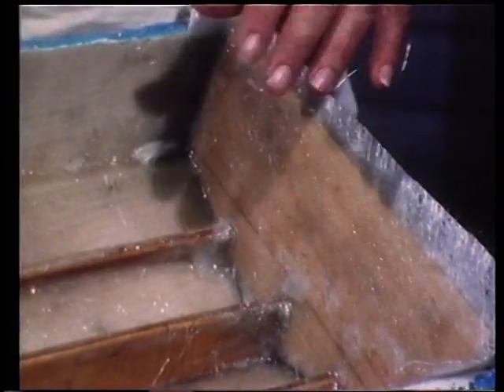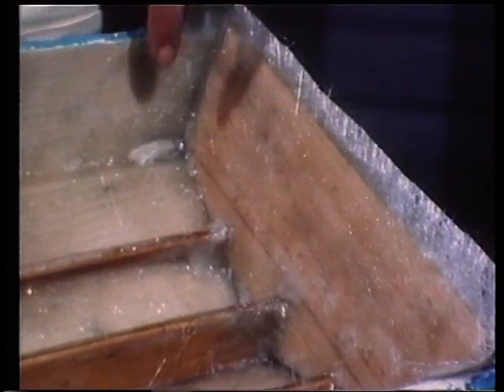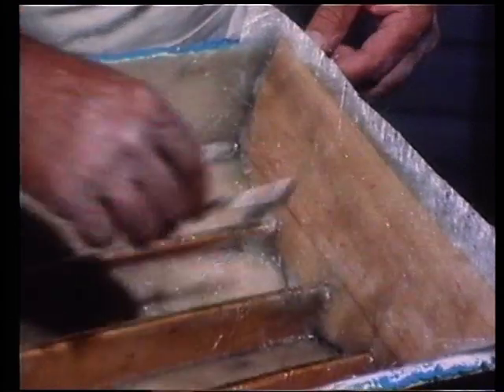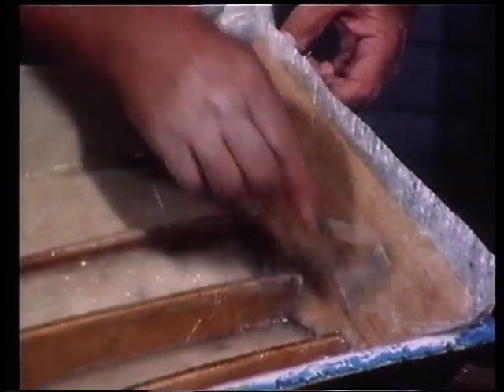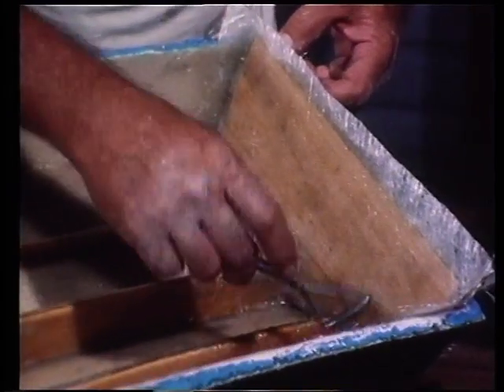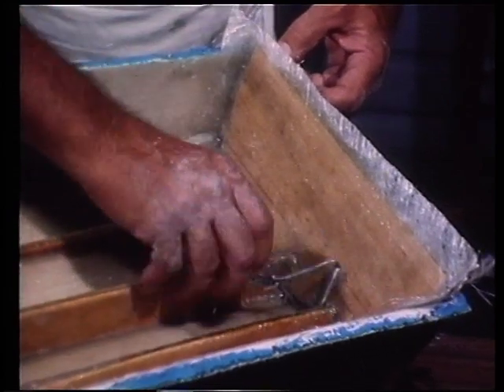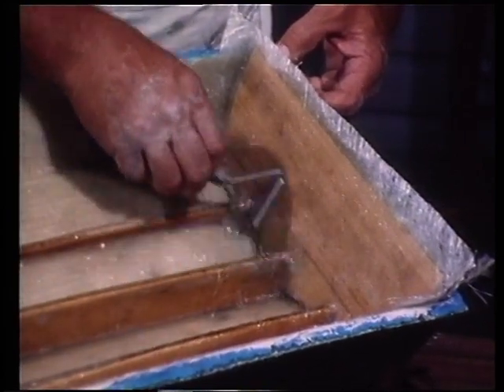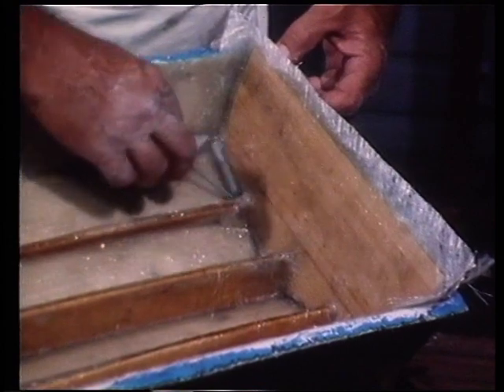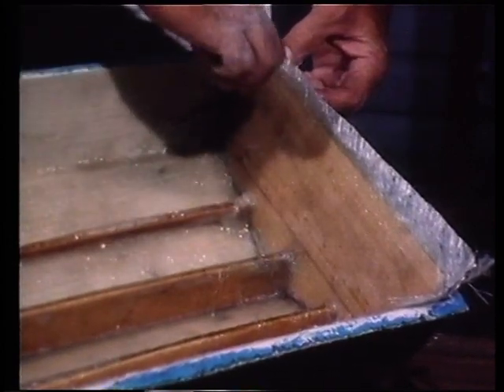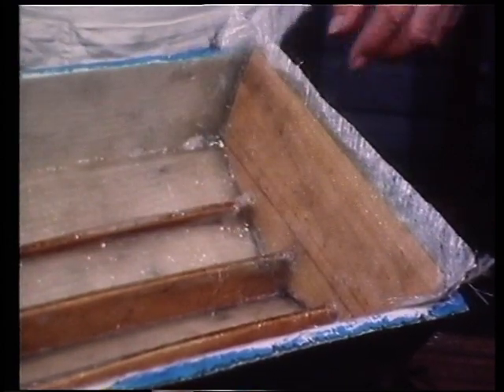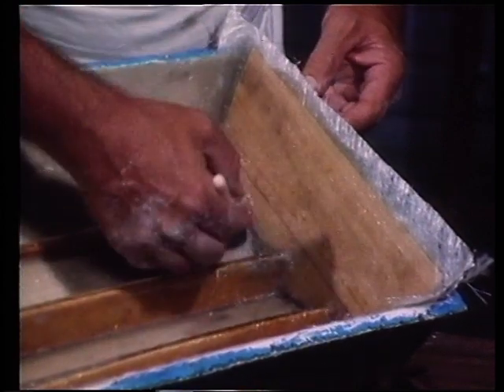But when you're doing it, make sure that you allow plenty of overlap areas so that the sides overlap the transom, the transom overlaps the sides, and particularly down the keel and chines. Now that means that you effectively get double thickness and therefore double strength in all of those areas, which is really a great asset and is part of the overall structural setup of whatever article you're making.